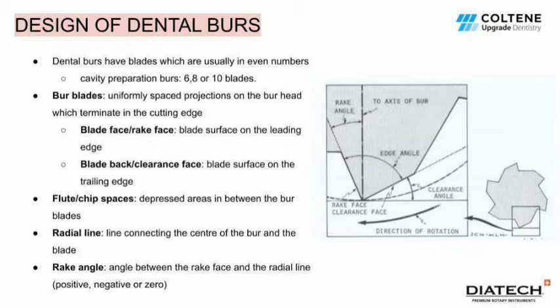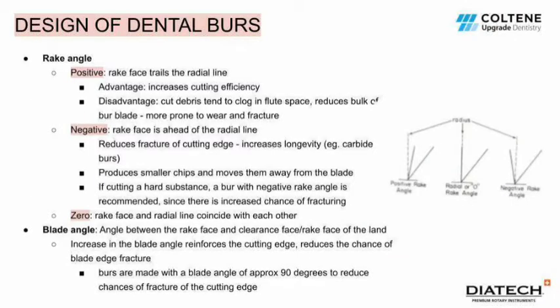The radial line is the line connecting the center of the burr and the blade, and the rake angle is the angle between the rake face and the radial line. This angle can be positive, negative, or 0. In burrs with a positive rake angle, the rake face trails the radial line. The advantage of this is that it increases the burr's cutting efficiency, but the disadvantage is that the cut debris tend to clog in the flute space, and the bulk of the burr blade is reduced with a positive rake angle, which makes the burr more prone to wear and fracture.